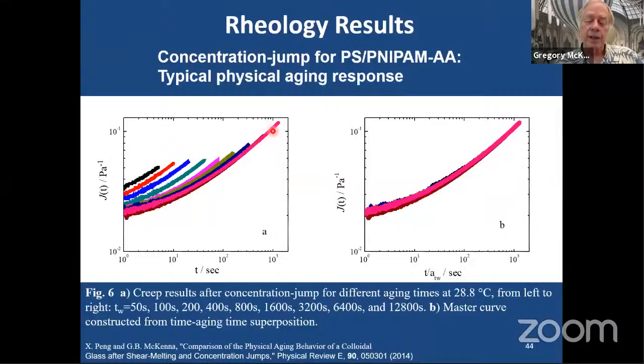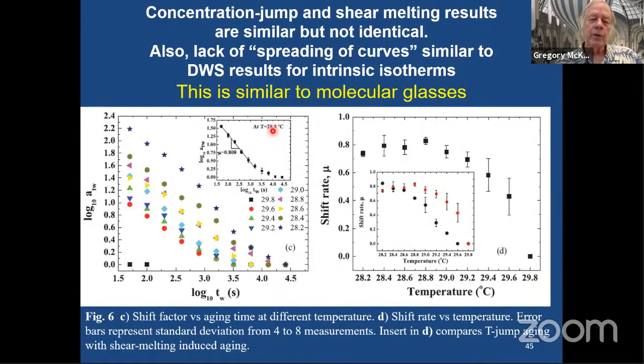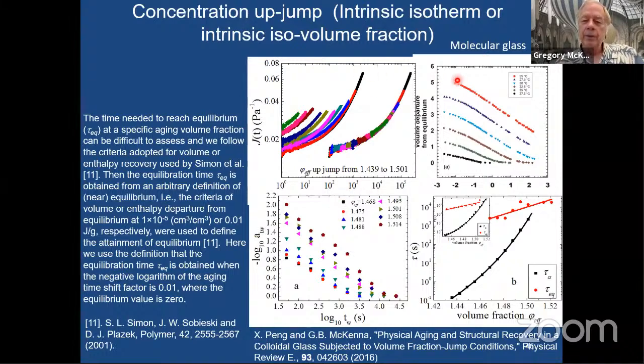And so the shift factor is indeed a scaled relaxation time. And we can do that for the spreading of the curves. It's different, we see, in the down jump than what we saw in the intrinsic isotherm. This is similar to molecular glasses, but it's not as extreme. So this spreading isn't as extreme as what we see in molecular glasses. And what we see here is something we also see in molecular glasses, that shear melting and physical aging itself have different kinetics of recovery. Okay, so that's an important thing. And we see that in molecular glasses and in the colloidal glasses, soft colloids. But we see here this spreading isn't nearly as great as in the molecular glass.